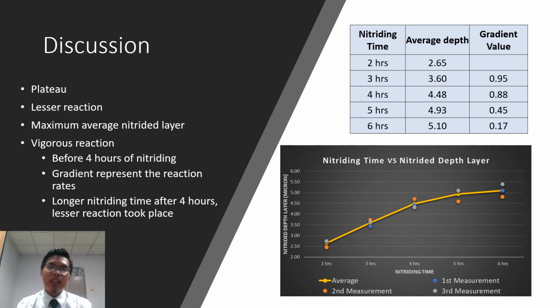So the discussion for the result is that the trend for nitrided depth layer becomes plateau after 4 to 5 hours of nitriding time. This indicates that there is a lesser reaction between the magnesium and nitrogen after 4 to 5 hours of nitriding time compared to the nitriding time before 4 hours. So it is expected the maximum average nitrided layer is around 4 to 6 micrometer. This shows that the nitridability of magnesium is around 4 to 6 micrometer for every layer.